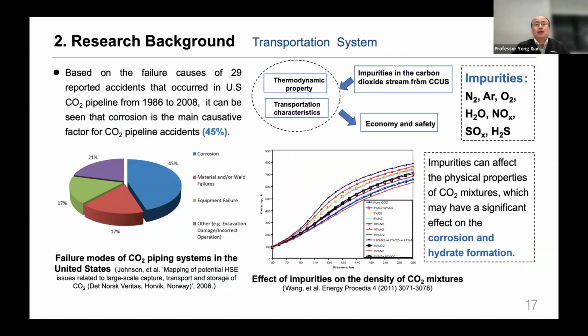So to the next part, that is the transportation systems. Also in the USA, they have a lot of CO2 pipelines, I think more than 6,000 or 7,000 kilometers. There are statistics from this year to this year, more than 20 years. They have only 29 reported accidents. Actually, the number is not very large, but you can see that for the CO2 pipeline, the corrosion causative factor is about 45%. So corrosion is a big challenge for the CO2 pipelines. We have to address these problems.